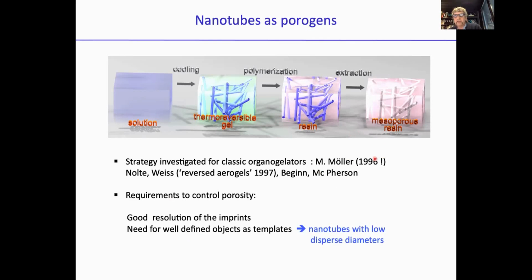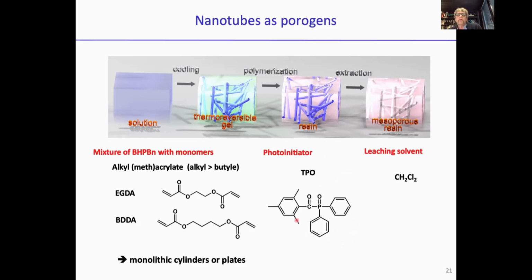When this author tried to develop this object, they had an organogelator with a huge size and diameter distribution. That's why we took advantage of having nanotubes with low dispersed diameters to see what kind of imprints we can have. And this is technically how we did it. These are the monomer and cross-linkable monomers used. This is the photo initiator to make the photopolymerization here, and the leaching solvent was a chlorinated solvent.